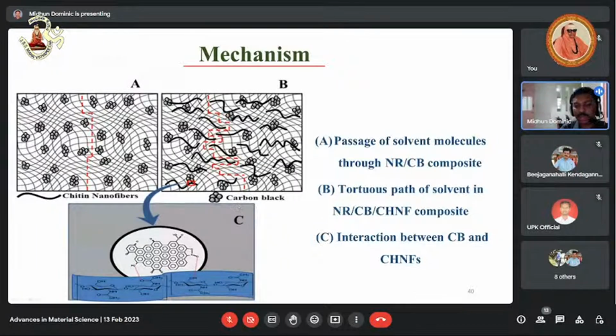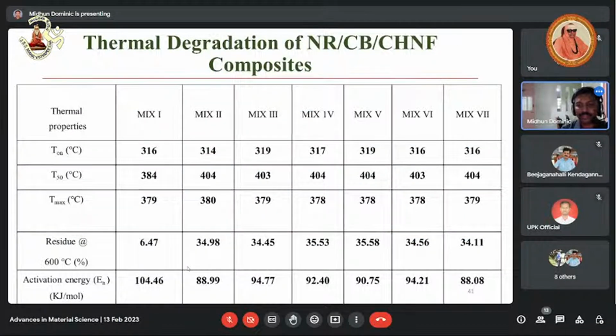Carbon black has several functionalities, and chitin nanofiber also has several functionalities. So intermolecular hydrogen bonding is possible, and network formation will be there. The three-dimensional network formation is responsible for the improvement in the mechanical properties. Regarding the thermal stability, there is not that much change. It is almost 404, 403, 404. So thermal stability is almost constant.